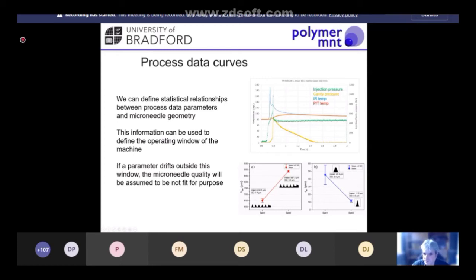And then that drops down to what we call a hold pressure. So we just sustain the pressure on that part to compensate for shrinkage as the material starts to cool. But then we can also measure the infrared temperature of the surface of the component. So this blue line here, we can measure the surface temperature of the part. And we can also measure the cavity pressure. So the pressure inside the mold cavity itself is shown in the yellow line here.